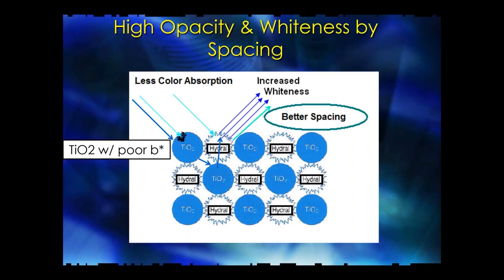So unfortunately, in this white, you can get very slight impurities that absorb the light, represented by this light blue material, that's absorbing into an impurity. And usually these are iron impurities. Very powerful impurities are chromium. And that's just from the process that is in there, and vanadium. So these things are purposely excluded to make very pure crystals. Now this B star refers to an LAB, and B is how blue the product is. So if you have poor B star, it means it has a yellowish type of color.